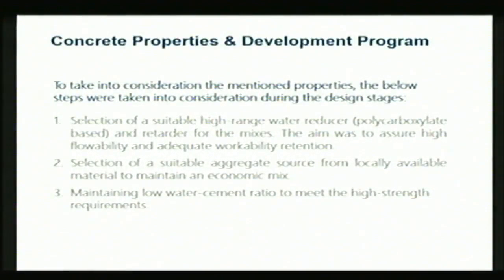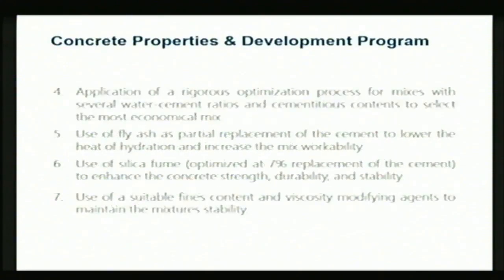First, we had to use the right admixture. So it's a polycarboxylate-based admixture, of course, but we had to add a retarder to make sure we had the retention. This is hot weather concrete, and it's not something you would just play with, especially when you have the core walls, and sometimes they take time. The aggregate was the key for the modulus of elasticity, and I'll talk about it in a while. You want to make sure that you had the water cement ratio low, to achieve the high strength requirement, but if it was too low, you'd have other problems with the pumpability. So that was another balancing act required.